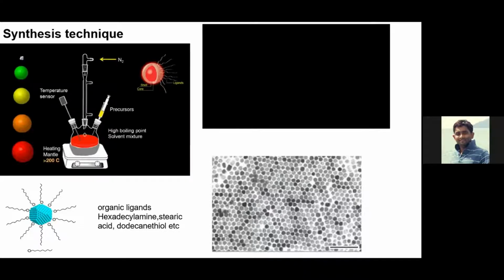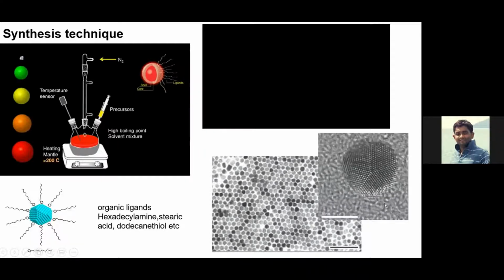And you can see this is only one example of the size of the particles. It's around 7 nanometers, and it's homogeneously dispersed, and you can see all the particles look the same. There are a few smaller particles or triangular ones, but these are very few. All particles look the same, and it's very crystalline. You can look at that, these are highly crystalline, and you can see the atoms in the crystals. At nanometer scale, 5 nanometers, when it's very crystalline, you can see the atomic level of the crystal.